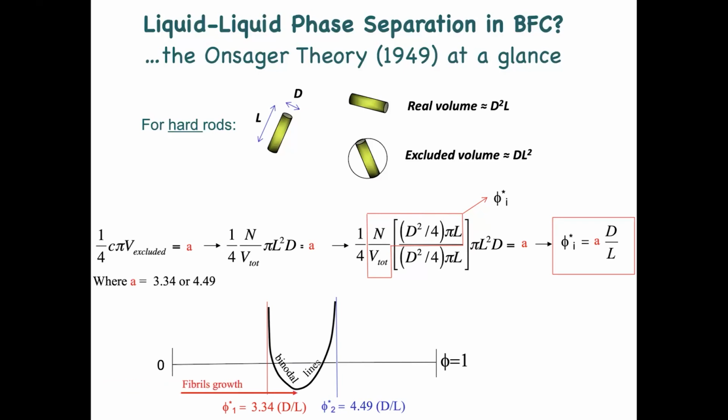Well, you can do it two ways. You can have filamentous colloids grow, or you could start with something which is very long and it's broken down. In both cases, from left or right, you go from one phase to a two-phase system. This is a bit counterintuitive, simply because this is the inverse of the aspect ratio. But if I now renormalize, this is the volume fraction that appears here, times the aspect ratio. Now this reduced volume fraction can be very large because the aspect ratio is very large. And now you see this is in the right sense.